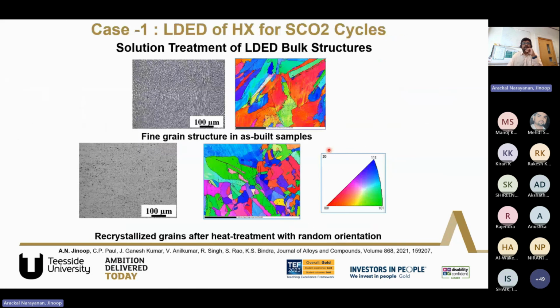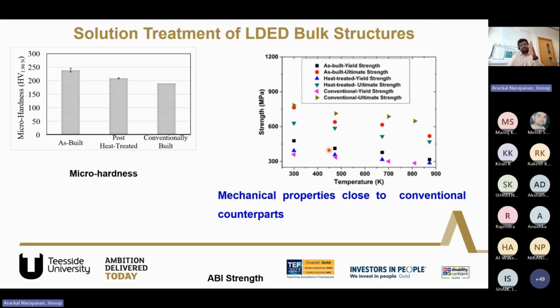And the other study that we did was on heat treatment of these materials, basically to get a homogeneous grain structure, as opposed to the refined grain structure that we observed in additive manufactured parts. So we got recrystallized grain structure at solution treatment, and then we compared the mechanical properties, and we could bring them very close to the conventionally built parts.